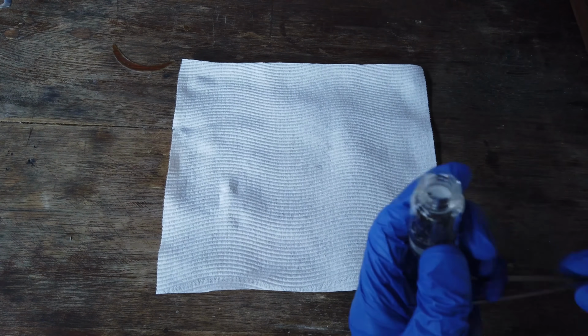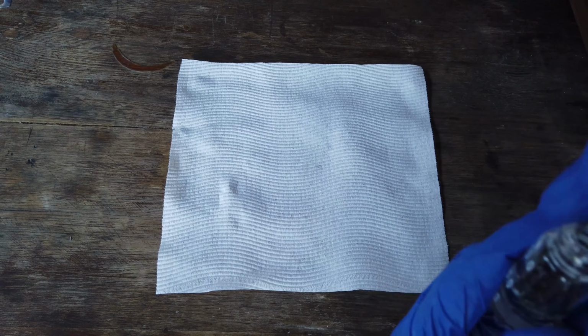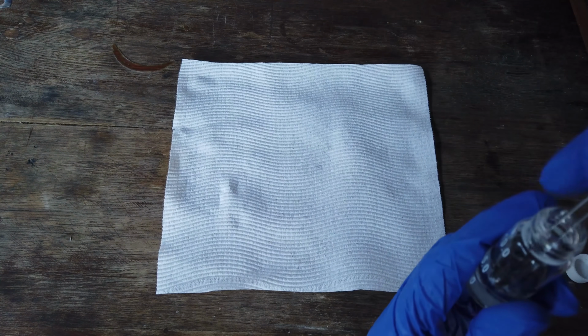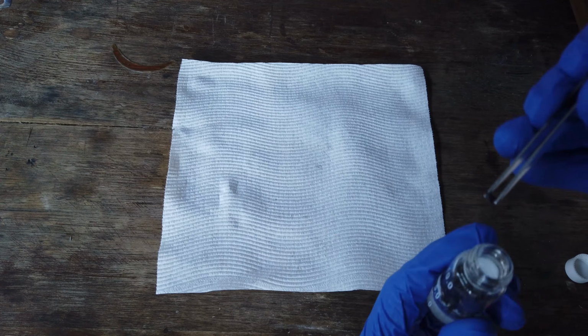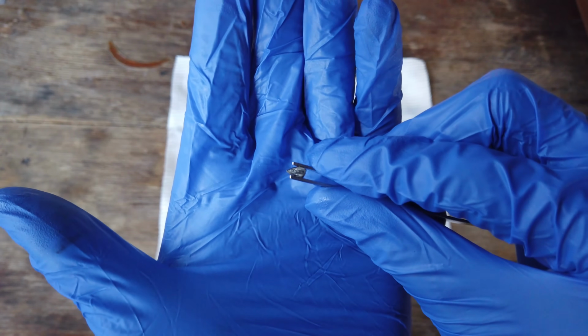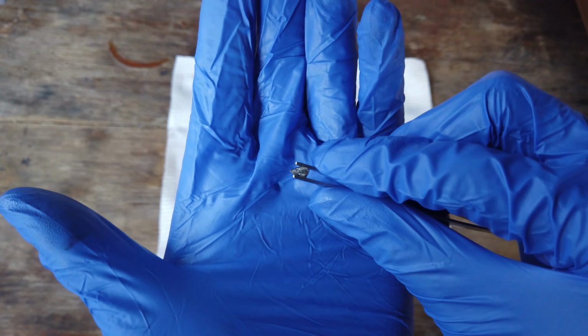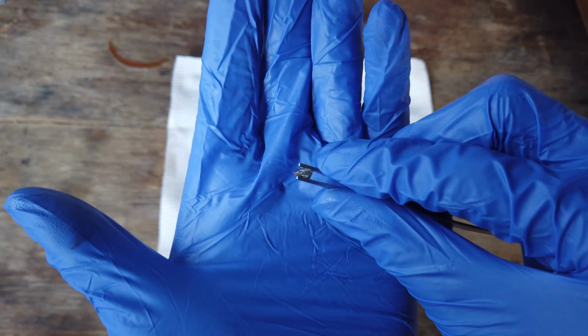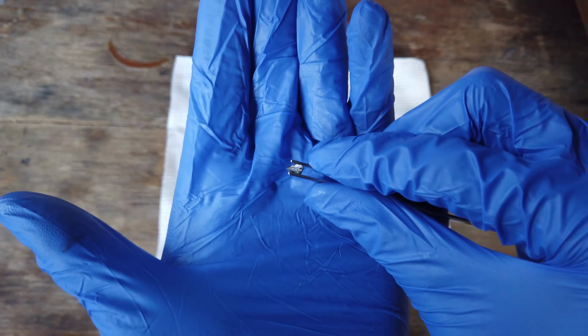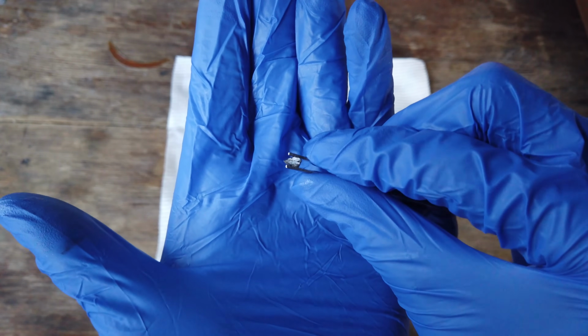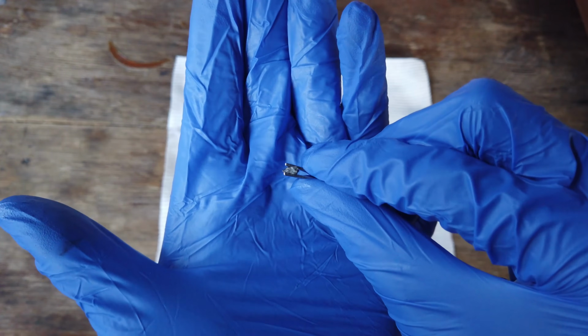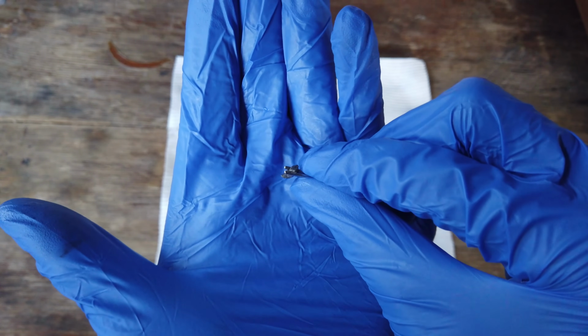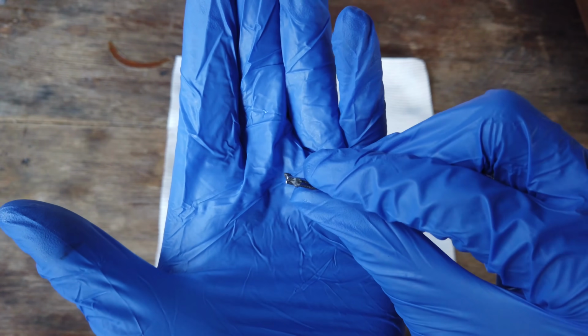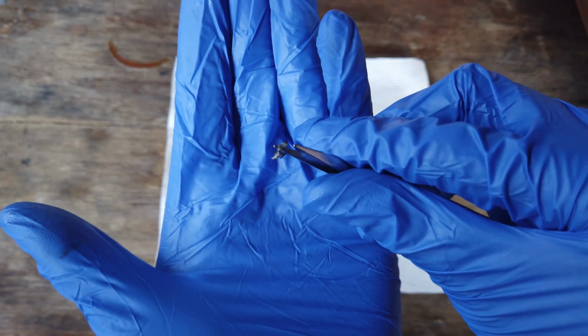The final thing that I wanted to show you at the very end of the video is if I get out one little bead of lithium, if I can grab it. That looks like a good one. One of the cool properties of lithium is the fact that it's quite a soft metal. It's not quite as soft as sodium as we looked at before, but it is soft enough to cut with a sharp enough knife and enough force. If I squeeze this really hard with this pair of tweezers, you can see it just kind of deforms and bends as a result of it being such a soft metal.